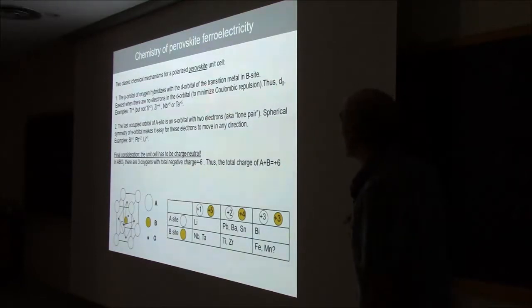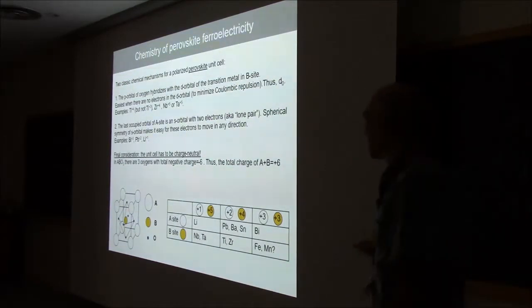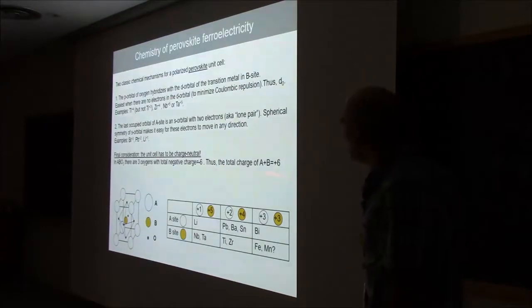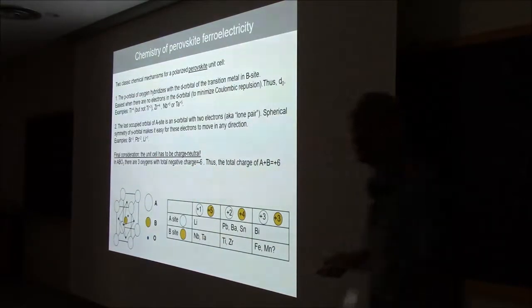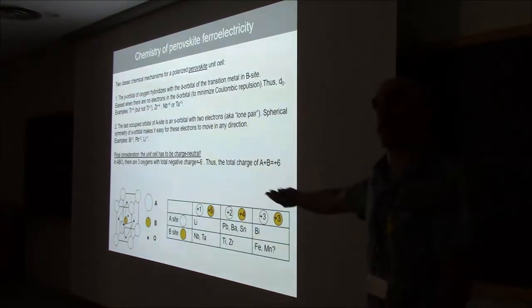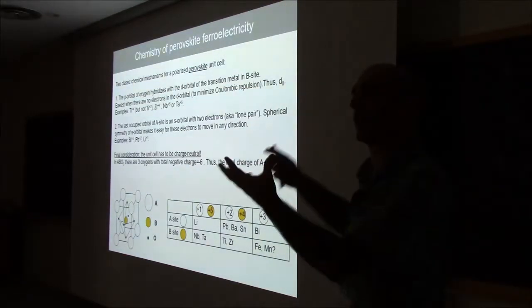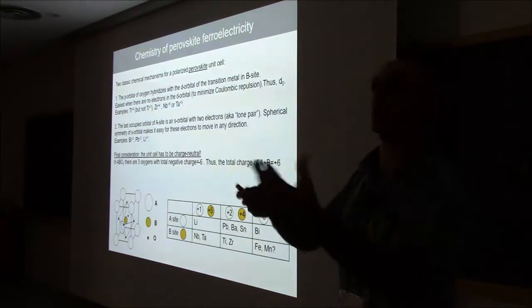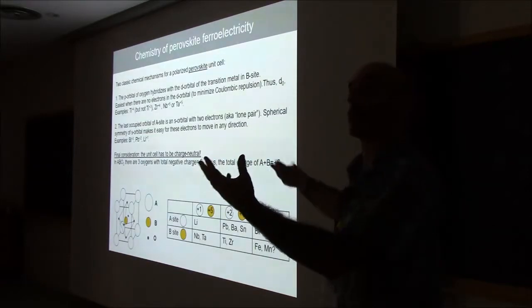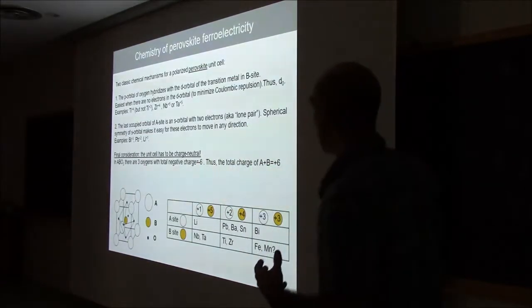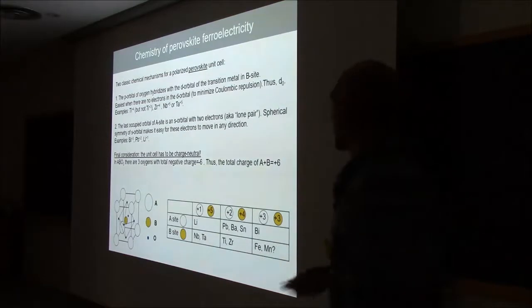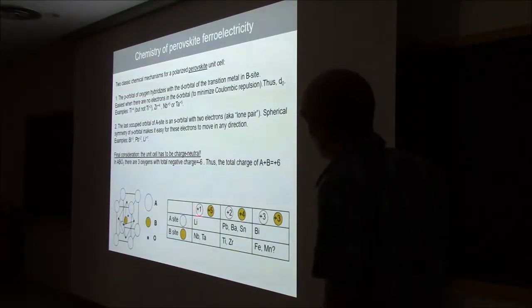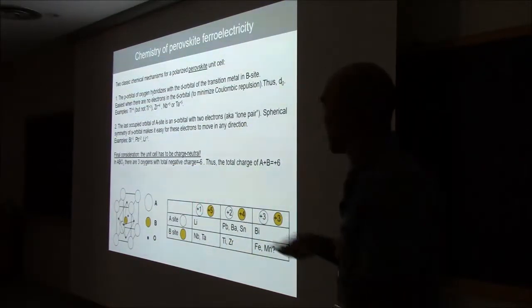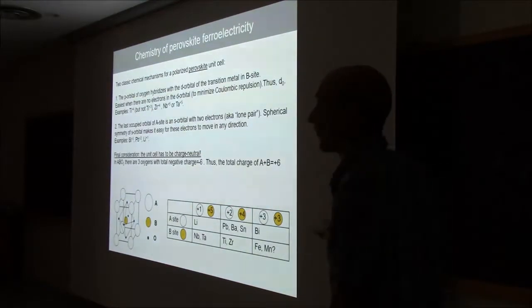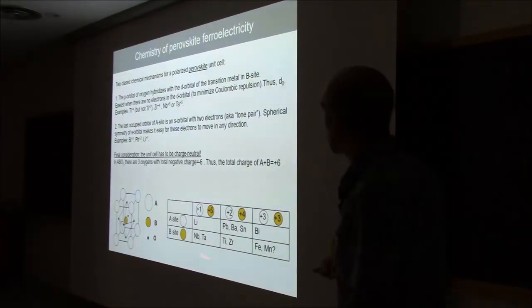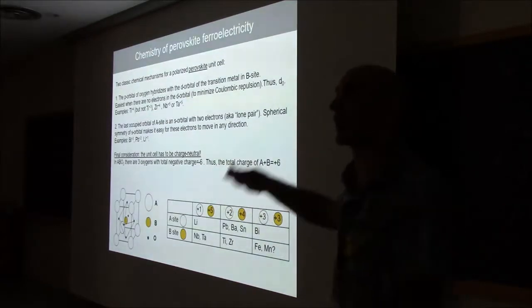And so with these tricks, plus the obvious consideration that the unit cell has to be neutral, you can have these kind of combinations of atoms that will give you a ferroelectric. Okay? So if you have 3 oxygens that have -2 charge each, you have a negative charge of -6. Then the A plus the B site have to have +6 charge, and so you can have +1 on the A site, +5 on the B site, or +2 on the A site, +4 on the B site, and so on and so forth. And these are some typical perovskite ferroelectric combinations.